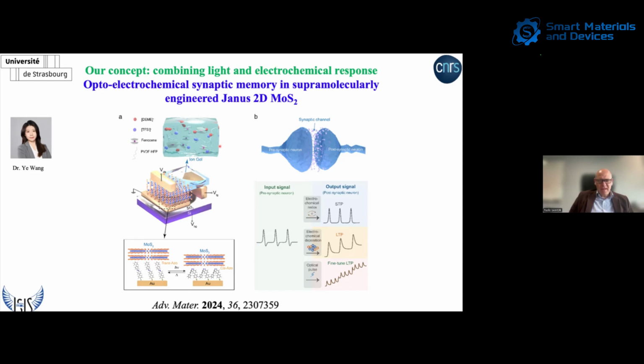They can be oxidized. And what Ye has been able to demonstrate is that, depending on the voltage we apply to our dielectric, that is our ionic gel, for low voltage, below 2 volts, each pulse can trigger a short-term plasticity, potentiation. Namely, as soon as the pulse is released, our system goes back to the initial current. Whereas at higher voltages, above 2 volts, each pulse triggers the field-driven accumulation at the interface with molybdenum disulfide of more and more ferrocenium molecules. This has a much longer lifetime and can be used to emulate long-term plasticity, which can be finely tuned by changing the state of the azobenzene.